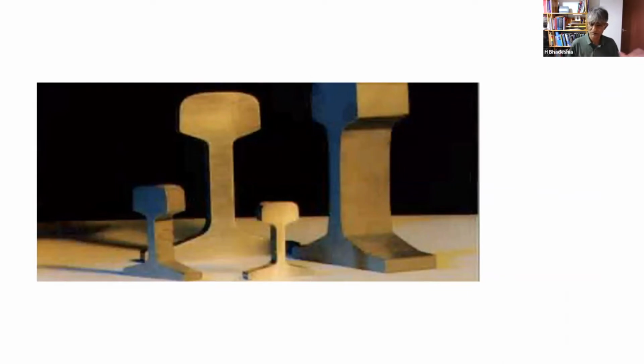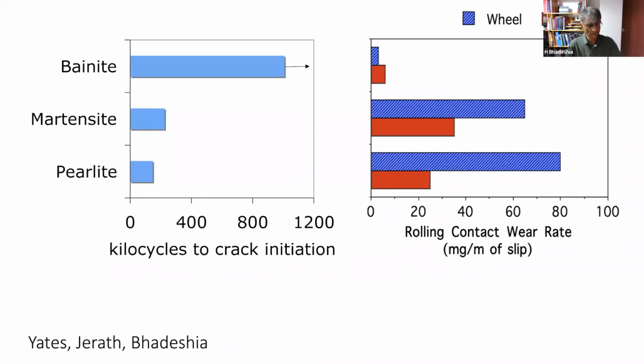It's in the compositions that I've just illustrated, because it has to be designed for continuous cooling transformation on existing equipment, because the existing equipment is very, very expensive. Okay, so we made it, and the rails were made by British Steel, and they were just remarkable results. There are two parameters which are really important in rails. One is the wear rate, and this is the only material which reduces the wear rate also on the wheel.